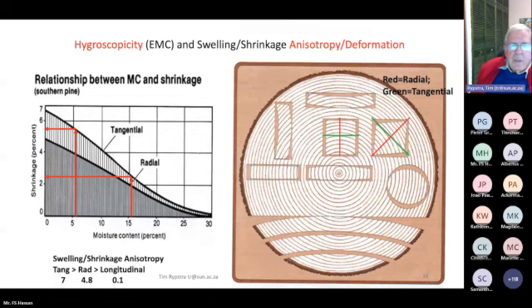Together with hygroscopicity or with moisture content changes, there is swelling, which is leading, as you would see on the right-hand side, if you take a cross-section of a tree like that, and you take a perfectly square piece of wood, then depending on where you cut that from the tree, you will find that the dimensional changes that occur with time are different. So this perfectly square one now has this cross-section shape, whereas this one, after drying, is less deformed or shrunk in that direction than it is in the tangential direction. Okay, to the right, another slide, please.